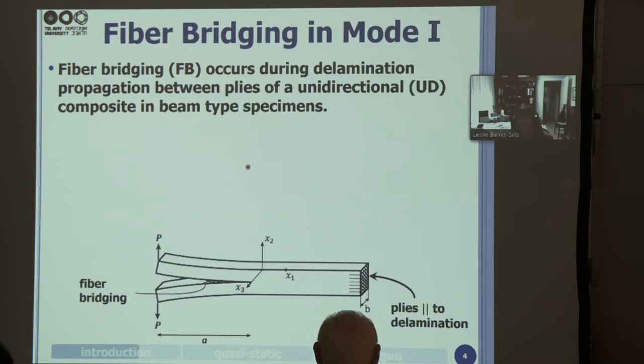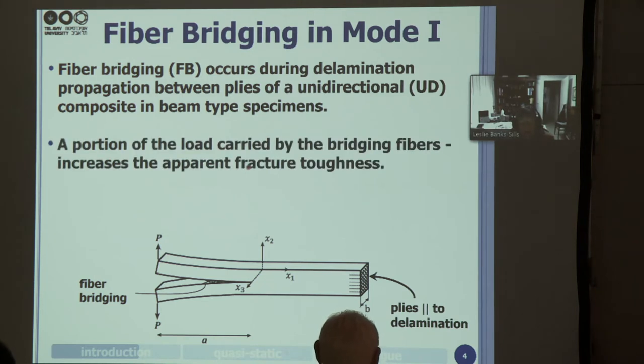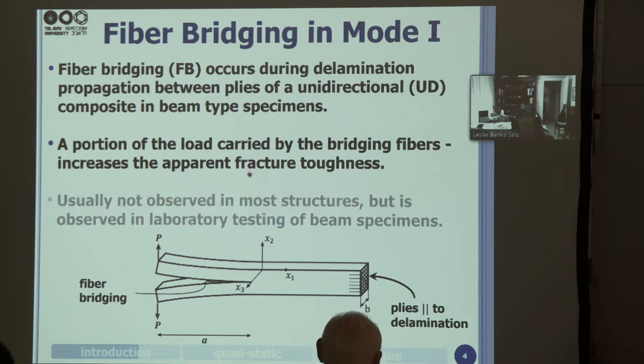So composite laminates are very important for us, but one of the problems when we test is that fiber bridging occurs in beam type specimens in the lab. And so a portion of the load is carried by the bridging fibers, which increases the apparent fracture toughness. Unfortunately, it adds to the fracture toughness only in the lab, usually, except for some wind blades, fiber bridging is not observed in most structures. So you have it in the specimens that you're testing, but you don't have it in the structures that are